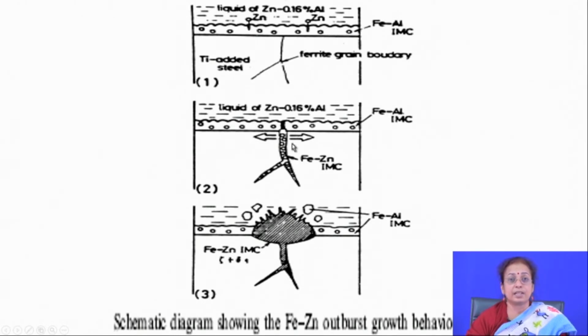phase. So, what happens is that this zinc gets diffused in through the grain boundaries. Naturally, there is always a chemical potential difference along the grain boundaries and between the grain boundaries and inside the grain, as a result of which zinc again goes on diffusing from the grain boundary to the grains. Wherever there is diffusion of zinc, it reacts with iron and there is iron-zinc intermetallic formation. So, intermetallic formations are there at the interface, as well as along the grain boundaries. Gradually there will be highly applied pressure on the grain boundary regions, and this intermetallic grows on the surface. So, after a while you will find that it applies a lot of pressure.